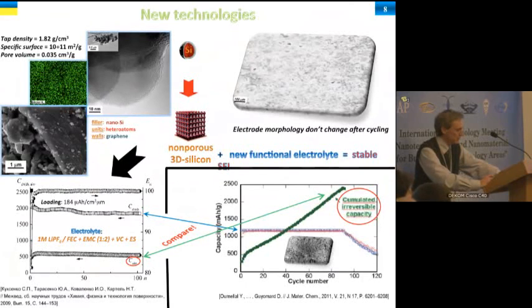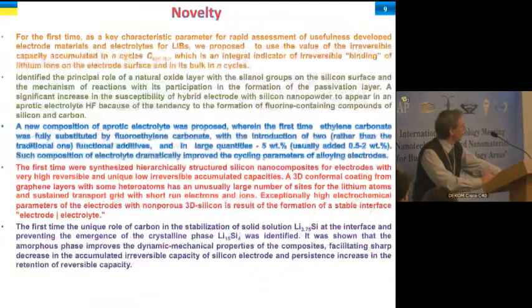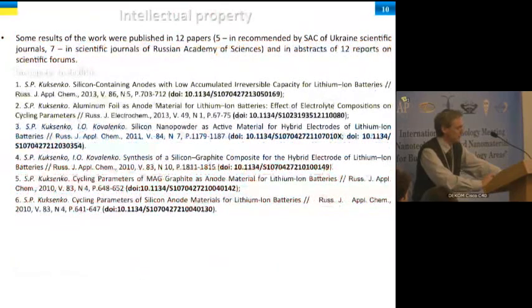The three-dimensional silicon electrode cycling parameters achieved loading capacity more than tripled compared to graphite anodes, and accumulated irreversible capacity equals only 1/4 of reversible capacity, due to high density of the electrodes and formation of stable electrode-electrolyte interface. One can see a comparison of our results with the best results published by our competitors. After the appearance of our publications in 2010 devoted to the effectiveness of electrolytes based on fluoroethylene carbonate, the demand for fluoroethylene carbonate on the market has increased dramatically.